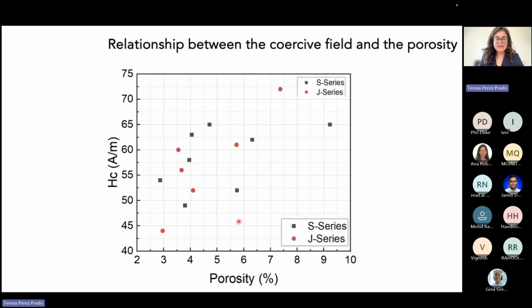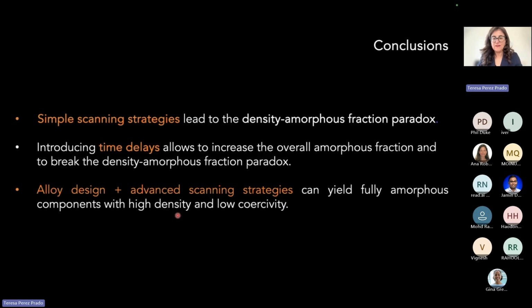And then just one final slide. For this series, if we plot the coercive field versus the porosity, we see there is some correlation here. Once we have a very large fraction of amorphous material, then other factors come into play that influence the coercive field, which are masked if you have a lower amorphous fraction. And there are several areas where we can work and keep improving. And with that, I finish my talk.